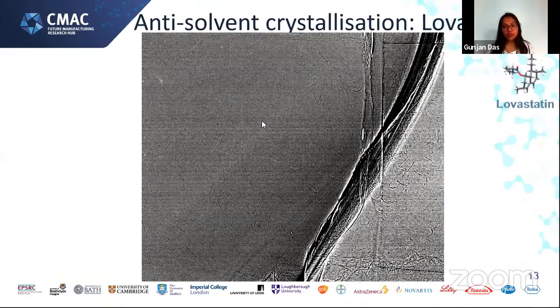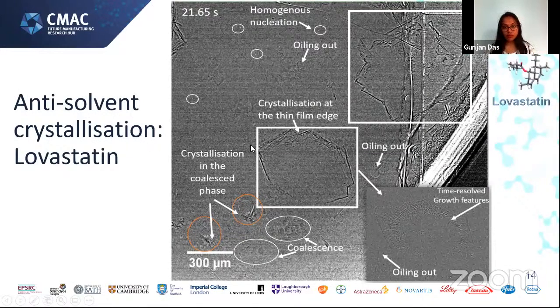So this is the image I was talking about. This is one of the still images taken from the video. We can see some spherical droplets joining together, and eventually they form this thin film edge, which then later on, when we watch the video, we can see the needles growing. One thing I also didn't mention in the video earlier, because things were happening at a very fast speed, is that there was also some homogeneous nucleation taking place at the same time, appearing as plain white little pixels or dots in the video.